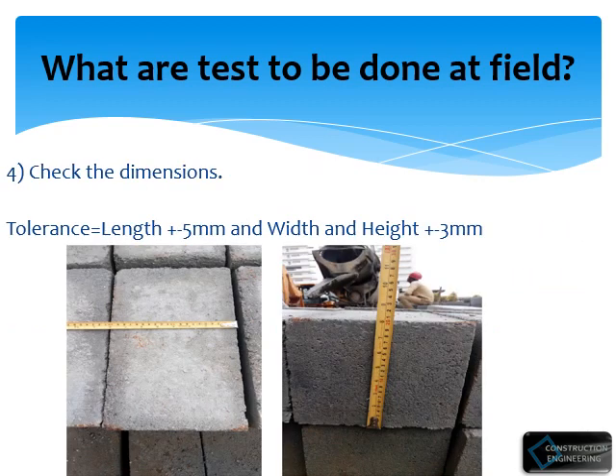Fourth, it is very important to check the dimensions of the blocks. The tolerance for length is plus or minus 5 mm. Width and height tolerance is plus or minus 3 mm. The picture shows the dimension checking image.